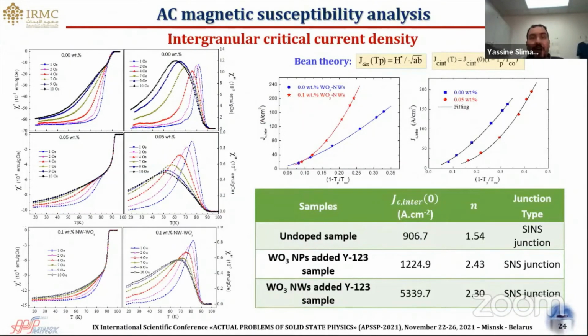Here we presented the AC susceptibility measurement as a function of temperature, which is useful and practical to evaluate the intergranular properties. The formation of the peak in the imaginary part of the AC susceptibility measurement curves originates from the energy losses caused by the penetration of magnetic fields in the intergranular networks of weak links.